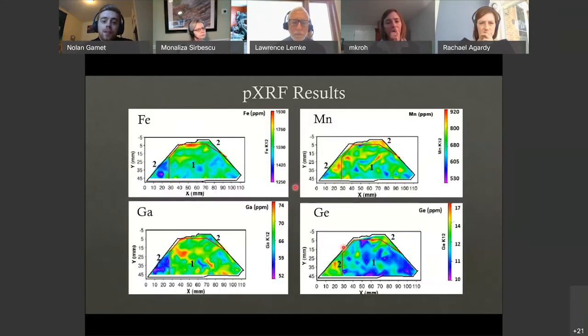These zones were then also carried on to iron, manganese, gallium, and germanium, in which iron and gallium, seen on the left, displayed similar variations compared to tin, and manganese and germanium were almost opposite, in which they mostly contained low counts in zone 1 and high counts in zone 2.